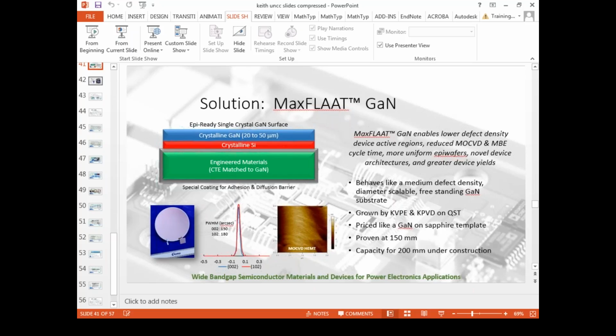But once you get away from cracking, Kyma offers a GaN on silicon product. We'll give you up to 0.5 micron of GaN. Anything after that, it cracks. Now you can put an innovative buffer layer in there like many groups have, and I think all the groups that have a GaN on silicon power device out there have developed one, licensed one, what have you. That's usually aluminum nitride, gallium nitride, AlGaN, superlattices, graded layers, and all that, just to mitigate some of the strain effects so the top part doesn't crack, but never do they get these thicknesses.